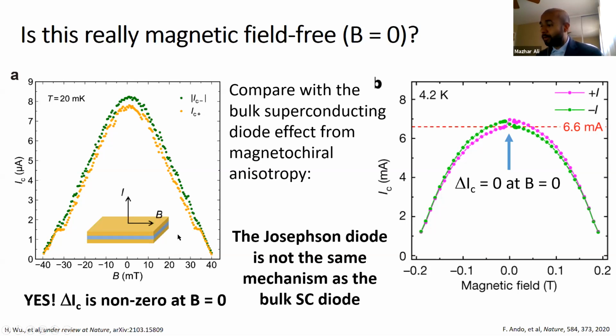At this moment, we also don't know, but our collaborators in previous work have always argued that this material should not have any remaining magnetization, in experimental work. It is only theoretical work, doing a low temperature ground state calculation with the finite size effect on the monolayer, that says maybe there's a ferromagnetism. But it's tough to take that and say, yep, there's definitely magnetization in the 3-layer or whatever.